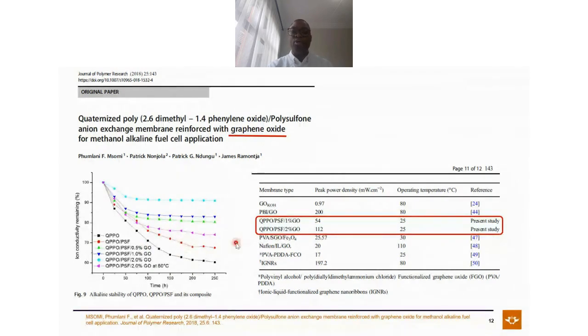Well, we took this membrane and put it against membranes found in the literature to see what our performance would be. The important part you need to look at is that we performed this study at room temperature, while other researchers were performing it at different temperatures. Some performed at 80, some at 100 and so forth. We performed it at 25, which is room temperature. And we're able to get one of the highest outputs in terms of energy. This one, which has 2%, at room temperature, gives about 112 milliwatts per centimeter squared. And when we compare to other material, which had about 197, bearing in mind that we were at 25, imagine if this was also performed at 80 degrees.